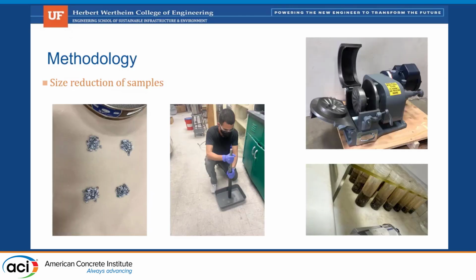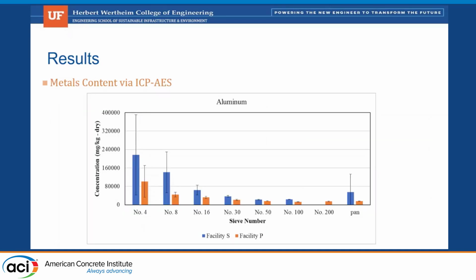And so poor Robbie there in the middle, one of my undergraduate students, is basically doing what we'll call a hand hammer mill, and then we went ahead and put that in the pulverizer once it was small enough. If you do decide to work with this stuff and you have those mills, make sure you use the ceramic plates, because it'll tear your metal plates to shreds in one pass.